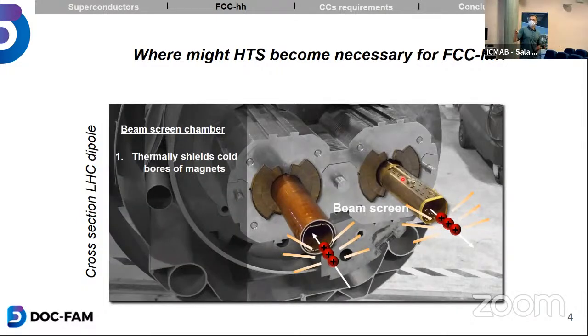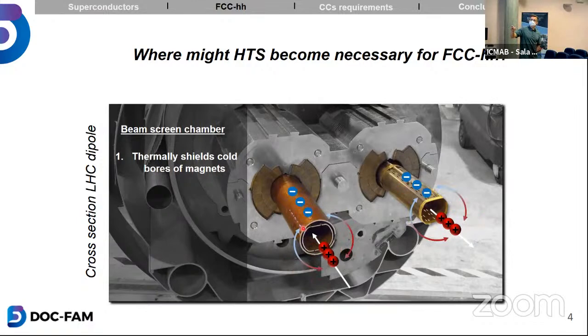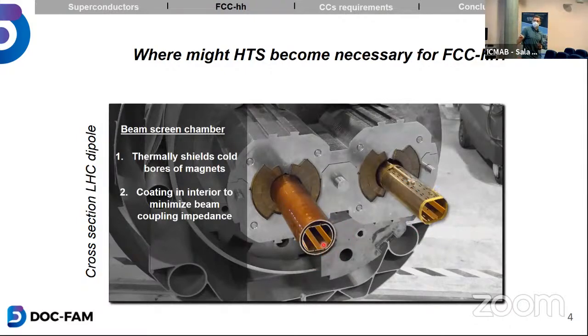so as I already mentioned, the purpose is to thermally shield the cold bores of the dipole magnets from the synchrotron radiation emitted by the charged particles. Now, since the stainless steel pipe is so close to the protons, mirror charges will be induced in the stainless steel beam pipe, and they will interact electromagnetically with the protons, which can cause beam instabilities. This cannot happen. For this reason, highly conductive materials are introduced in its interior. For the Large Hadron Collider, copper is in use. It offers a low enough resistance.